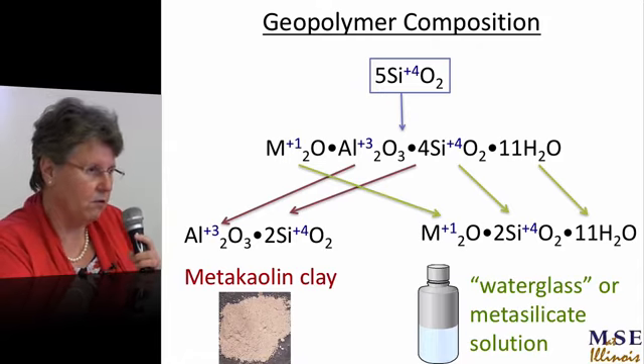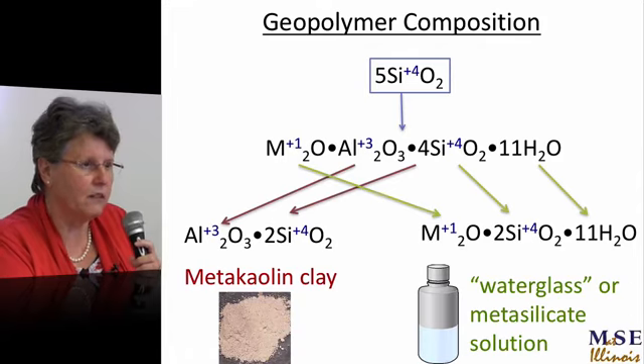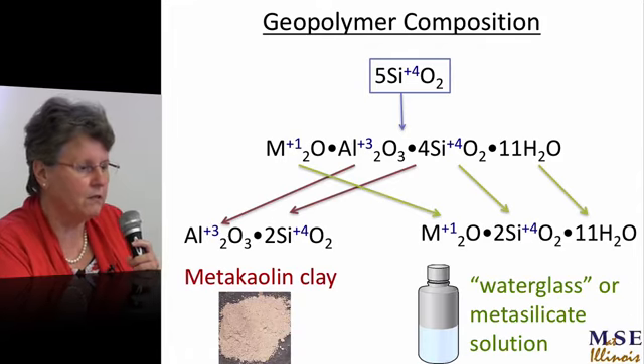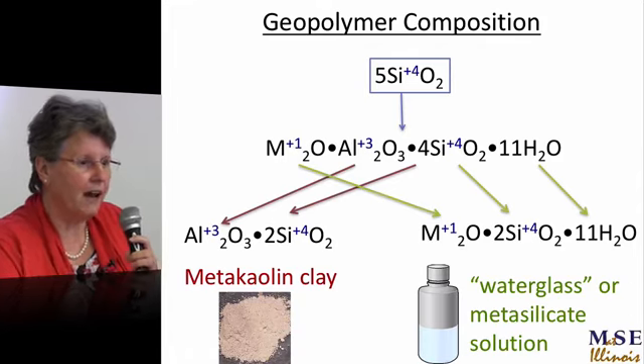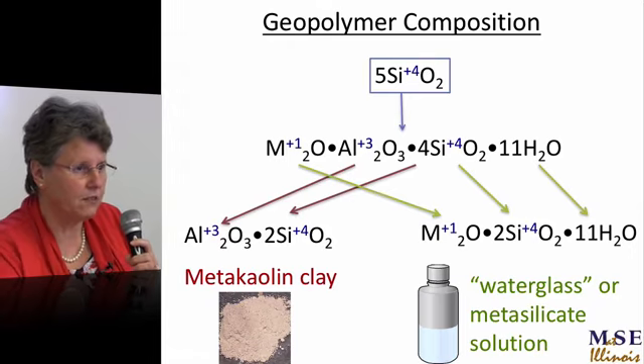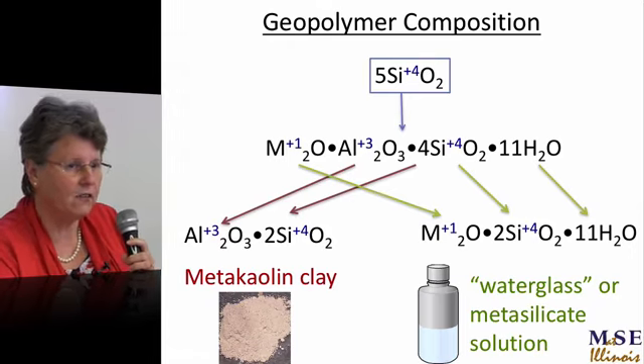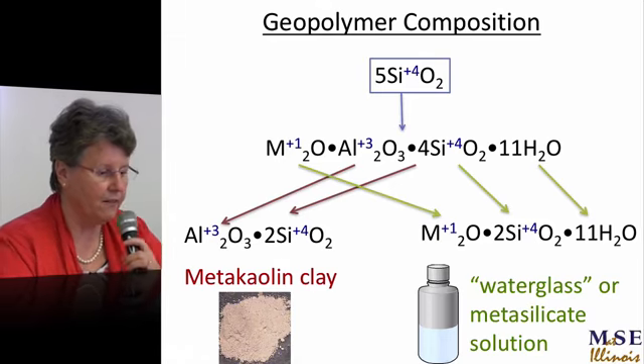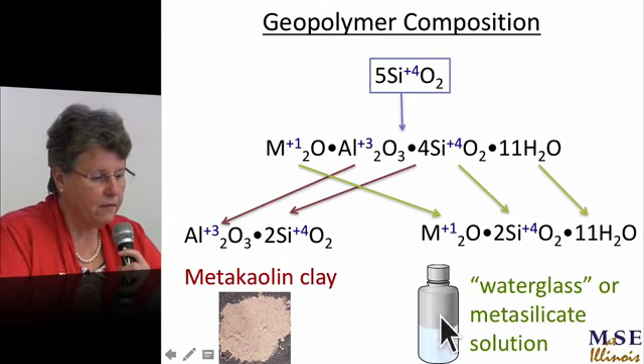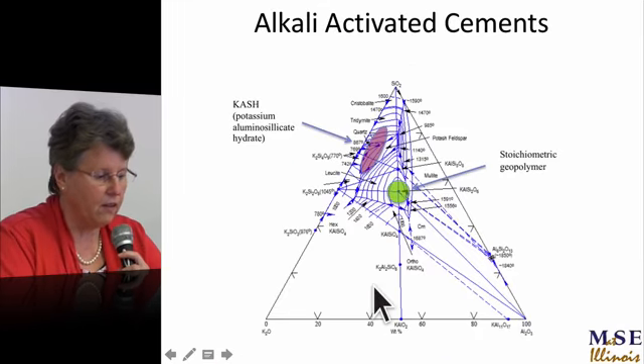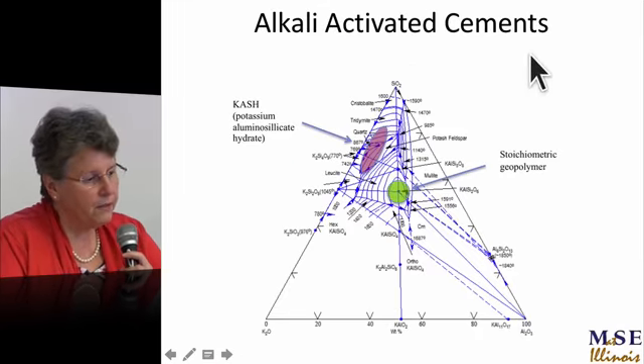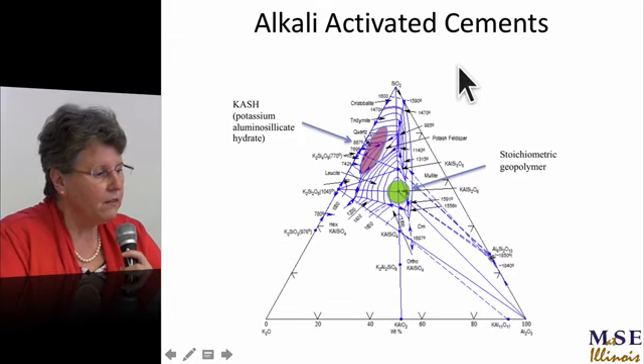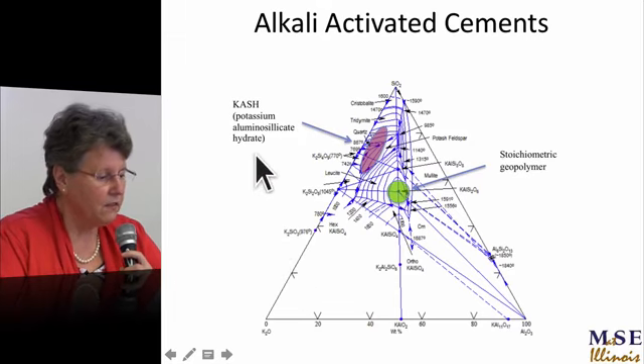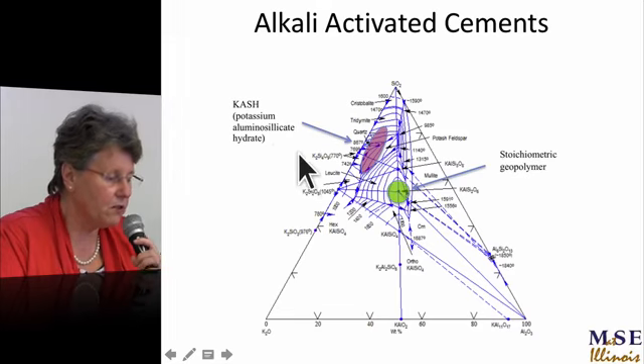various silica, Cabosil, in Illinois we got Tuscola, Cabosil, or ground up glass, so long as it's amorphous silica. It can't attack anything that's crystalline. It's not strong enough. And so that makes a solution, and that's water glass or sodium metasilicate, and that's the clay. Now, yes, the big long-winded confusion about alkali-activated cements, it's even more clear to me now after Joseph's talk this morning.